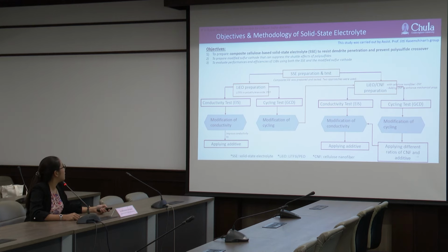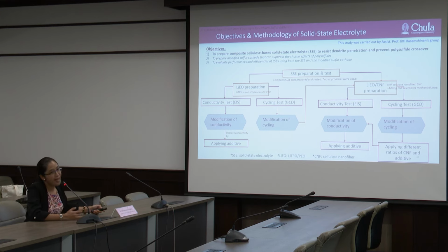In this work, the goal is to prepare composite cellulose-based solid-state electrolytes, or SSE, to resist dendrite penetration and prevent polysulfide crossover. We prepare the composite solid-state electrolyte and test via EIS, the conductivity test, and the cycling test, or GCD. There are two different systems. One is LiTFSI in polyethylene oxide, or PEO. In the other, we add cellulose nanofiber in order to enhance the mechanical properties. We also modify the conductivity by applying some additives.